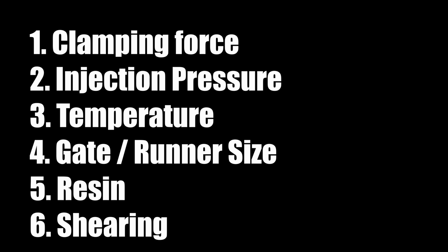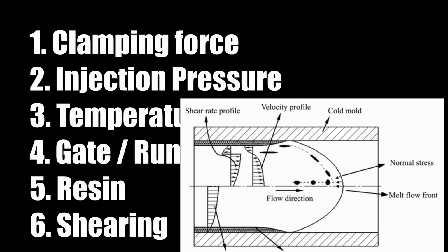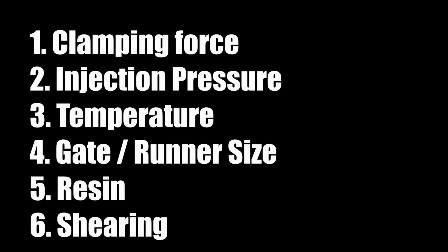And kind of as a related note, shearing effects are always important with resins, but especially important when working with clear resins. So shearing is when the individual chains of the polymer start to get ripped apart due to high pressures, either from injection or from differential pressures while going around corners or edges, or the difference between the wall of a mold and kind of the interior flow of the resin. So shearing is kind of a complicated subject. And the reason I bring it up is that shearing in clear parts is very noticeable because you can see actual defects because it's transparent. And this is especially important when you're trying to make a lens because any of those defects or shearing generates kind of stress concentrations, which will totally mess up the optics.